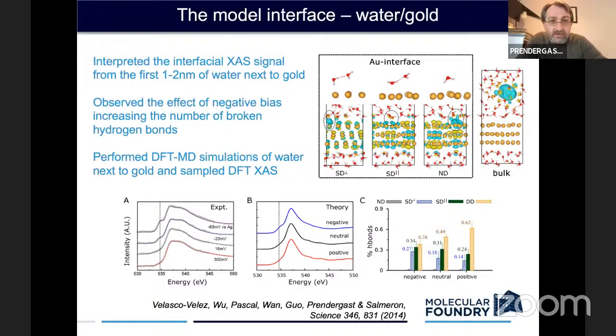And one of the most important aspects of that, you can see here some of these excitations of water molecules that I've circled here, here, here, and maybe here. If they're quite close to the interface, they strongly interact electronically with the substrate, with the gold. But if they're far away from the interface, they're somewhat isolated excitations. And so you can use that then to understand why the spectroscopy might be different and why certain peaks may disappear at certain voltages as you rearrange the structure of the water and even rearrange its hydrogen bonding structure.